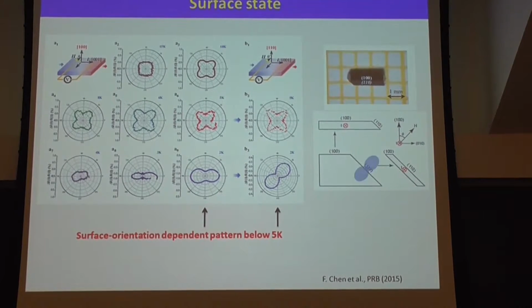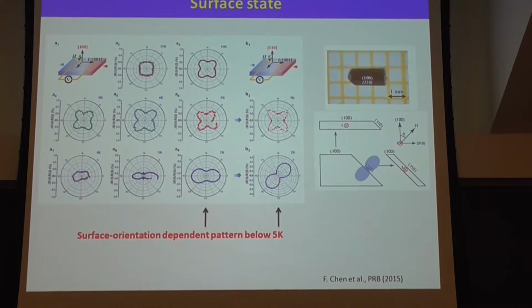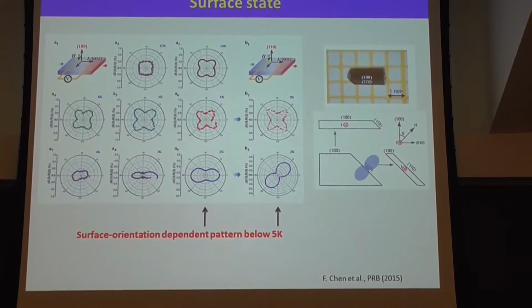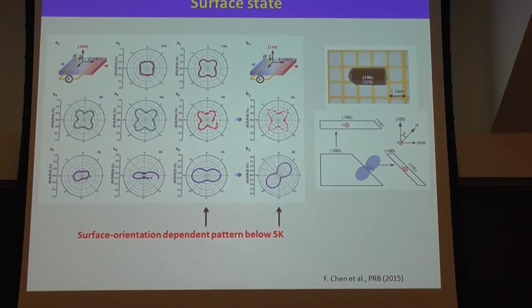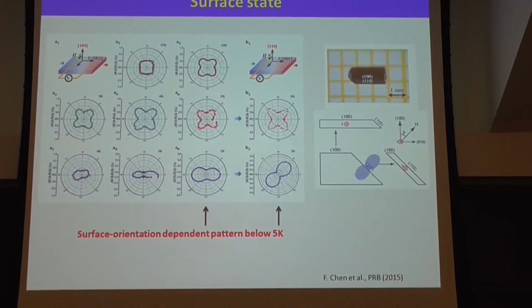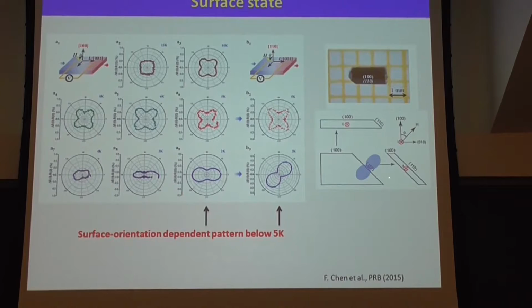But I changed from this surface to this surface, the 110 surface. But the phase just changed by 45 degrees. This is why here the phase is shifted 45. This definitely shows that this is the surface state. Even for a different surface, the phase is shifted. Okay.